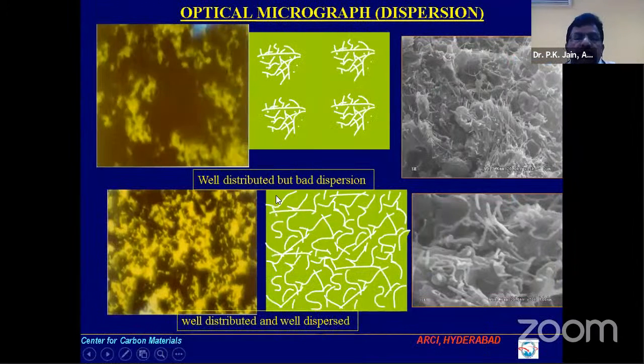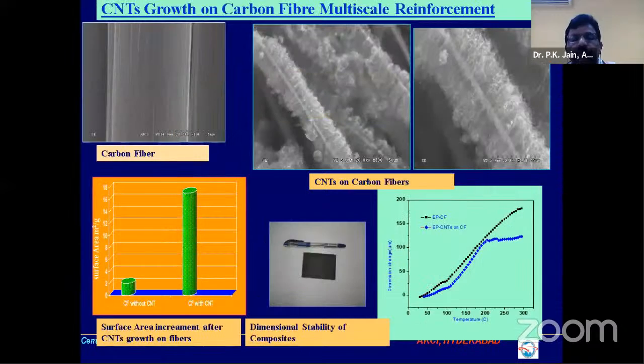Now as I told you, there is a difference between distribution and dispersion. If you have just added the material, it may lead to distribution but not dispersion. So you require proper functionalization to get better interfacial properties. The dispersion is required, not distribution. So one can grow the nanotubes onto the fiber, and then the dimensional control of the composite can be observed by doing this.